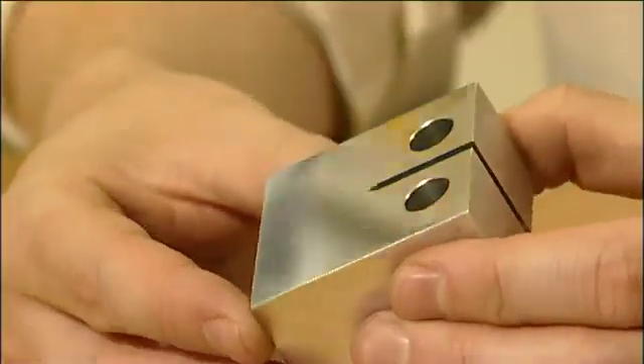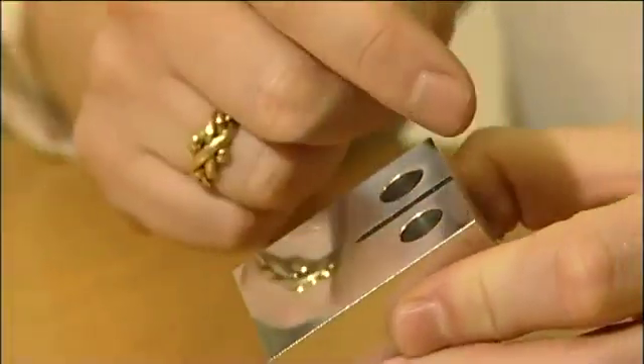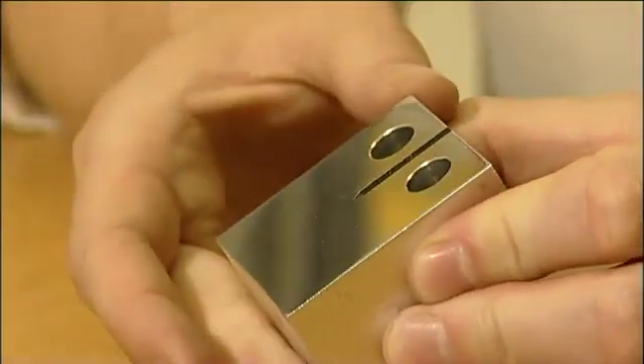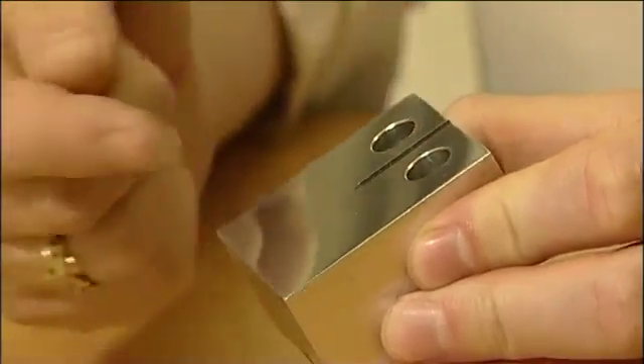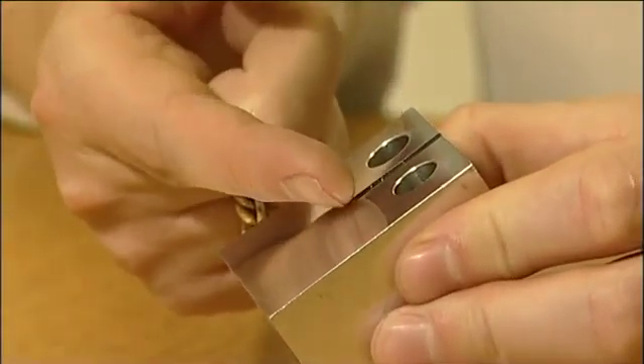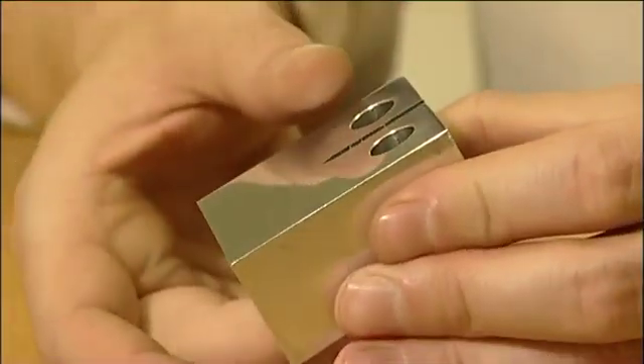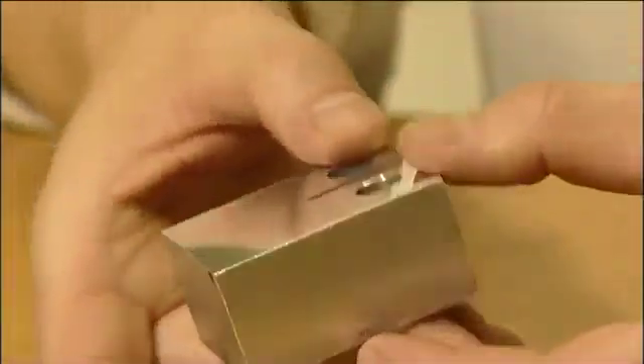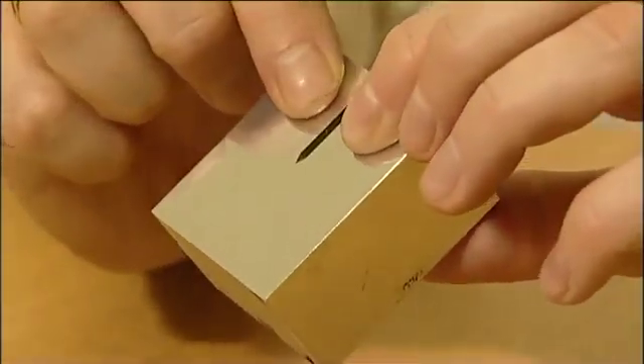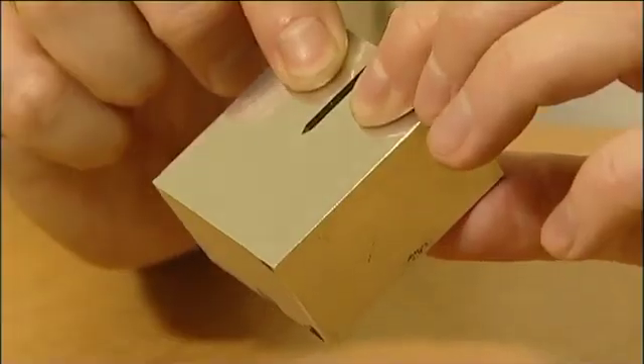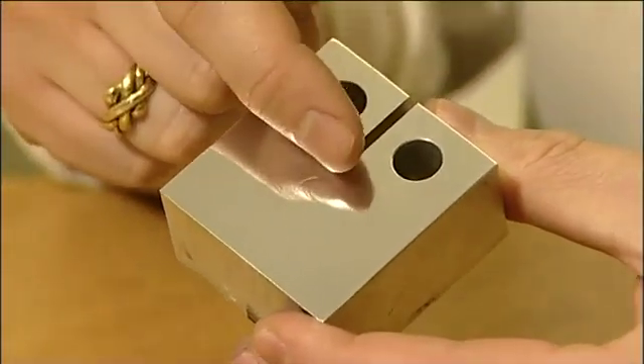This is the sort of sample that's used to measure plane strain fracture toughness. There's a notch that's been pre-machined into the sample, and a sharp fatigue crack would be grown from the bottom of the notch, and then using pins located into these holes, the sample would be pulled apart, would be fractured. Now you can see that the sample is relatively thick, and the reason that it's thick is to ensure that the crack is in a condition of plane strain.